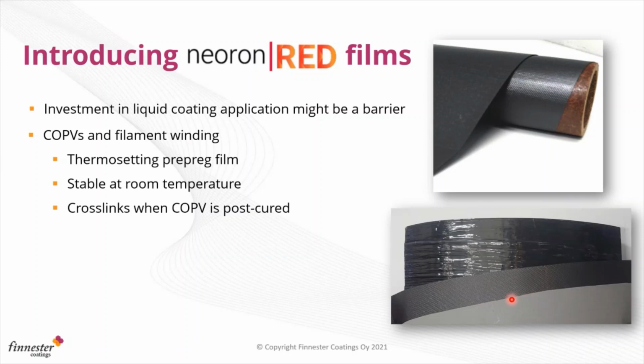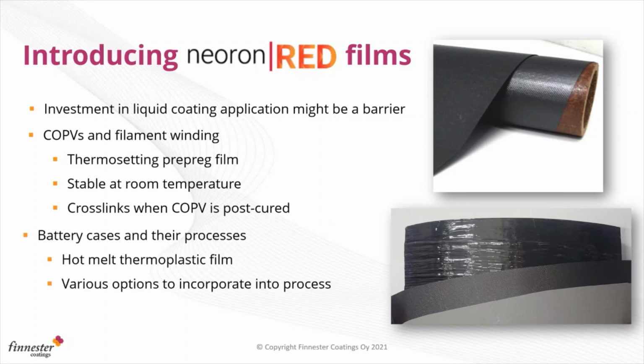When you apply this on your filament wound epoxy piece, it will cross-link itself, and it will cross-link with the epoxy during the post-cure process. But also for the battery cases and their processes, we have a film. A second variation of film is the hot melt thermoplastic film. This gives similar performance, but it will be thermoplastic, so it will be more recyclable and more fit for that sustainability aspect. There are various options to incorporate into that process. Like I said, one size doesn't fit all.